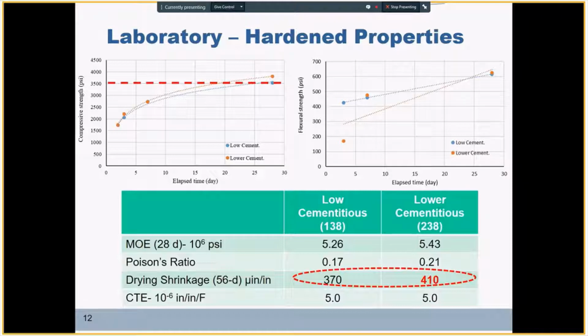The graph on the top left side shows the compressive strength development data, and the early age strength values here are very similar for the two concrete mixtures, which are in good agreement with the maturity data we observed earlier. The 28-day strength for both mixtures was higher than 3,500 psi, and the 28-day modulus of rupture flexural strength data was higher than 600 psi for both concrete mixtures.